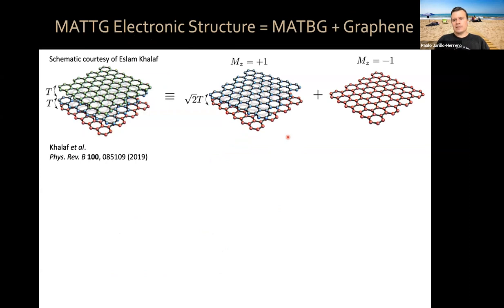So the electronic structure of magic angle twisted trilayer graphene is very interesting. If you take your three layers of graphene and you consider the interlayer tunneling T between each pair of consecutive layers, it turns out your Hamiltonian, if you do a basis transformation, becomes block diagonal into two blocks: one block which is magic angle twisted bilayer graphene-like, but with an effective tunneling which is square root of two times T, and then another block, which is just monolayer graphene.